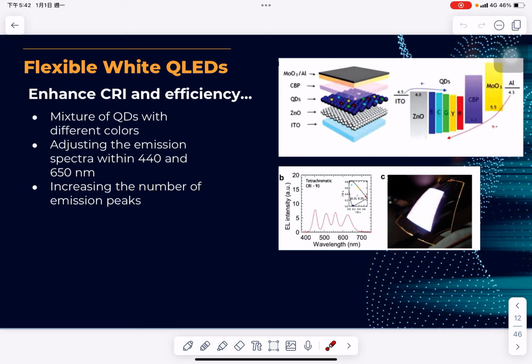Electroluminescence-based white QLEDs upgrade with mixed QLEDs, like this figure. This kind of structure improves EQE and CRI, adjusting RGB quantum dots in emission spectra, vital for human eye sensitivity, in between 440 nanometers and 650 nanometers. Narrow bandwidth boosts purity but lowers CRI. Raising mixed quantum dots from 2 to 4 significantly lifts CRI from 14 to 93 by filling more of the visible spectrum. You can see the CRI improved to 93 in this figure.